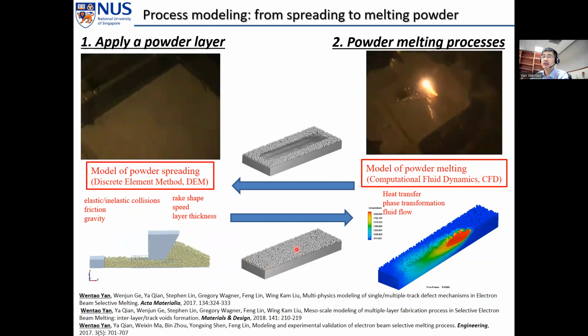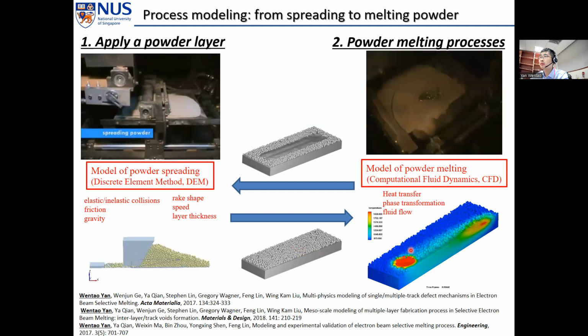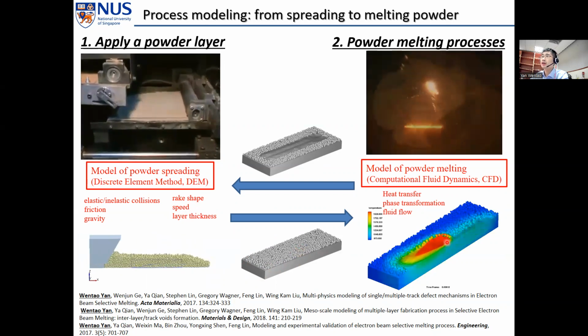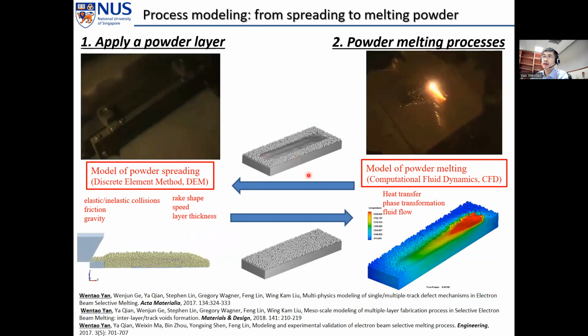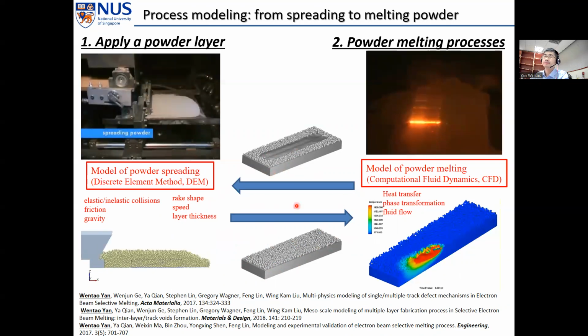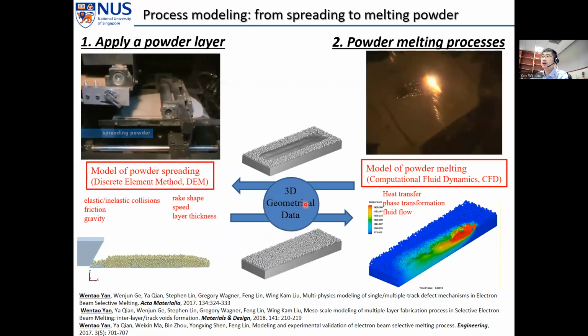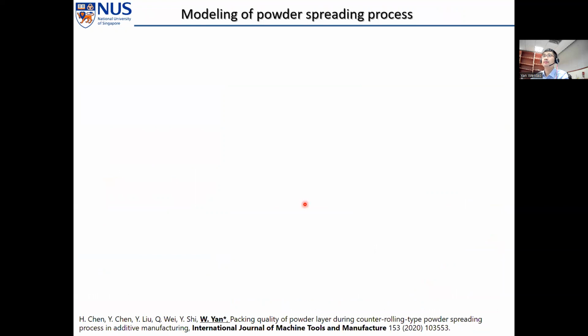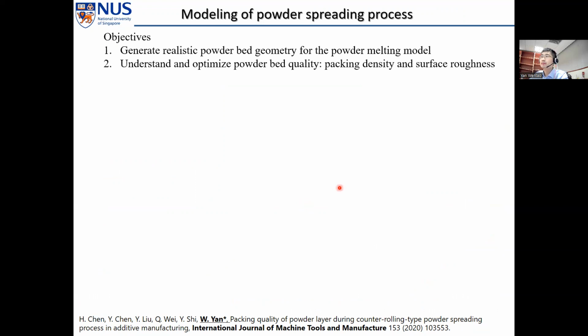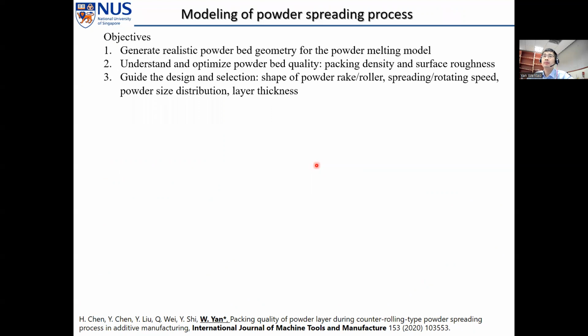With this model, we can get the configuration of the powder bed and implement it into the powder melting model to simulate the powder melting process, which can simulate the solidified geometry. And then we repeat these processes by coupling these two models together. We can repeat what's going on in the real experiments. In addition to generating realistic powder bed geometry, we can also use this model to better understand and optimize the powder bed quality, like packing density and surface roughness. And also we can provide guidance for the design and selection of a variety of parameters, like the shape of the powder rake or roller, spreading or rotating speed, powder size distribution, and layer thickness.